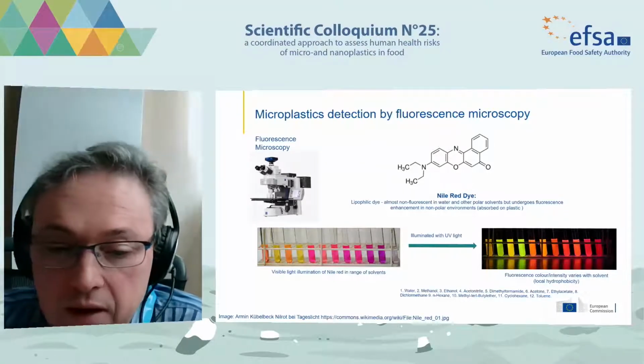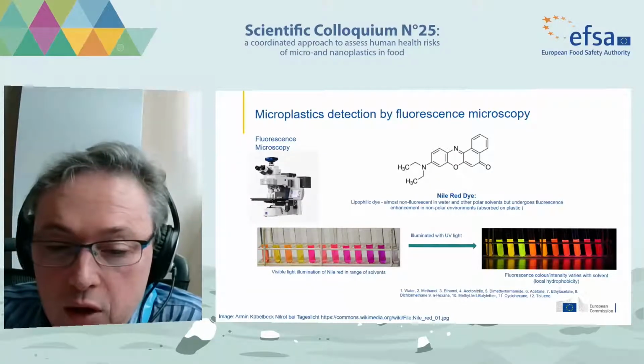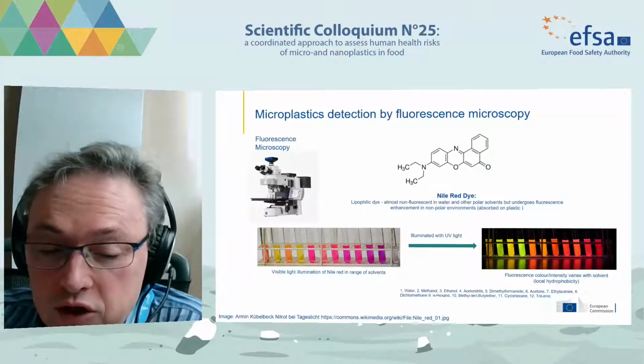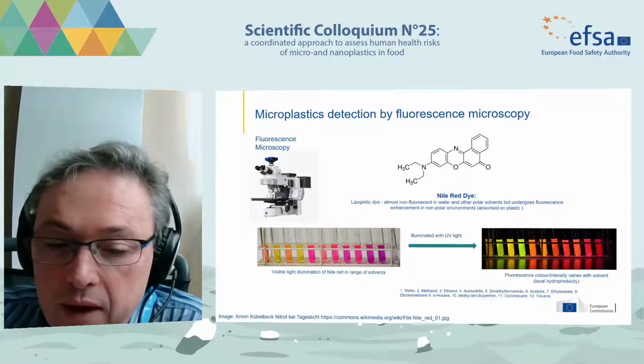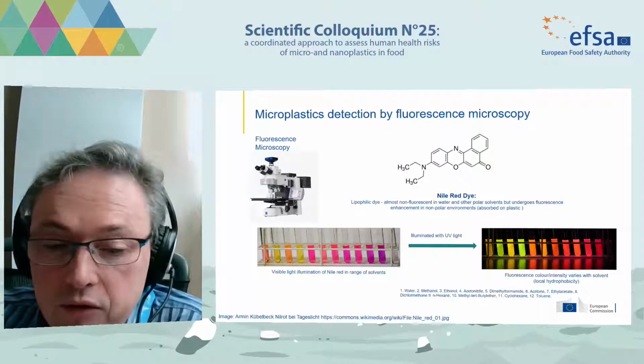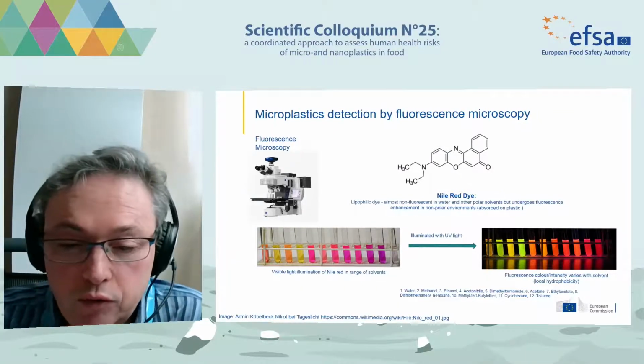In the photograph on the left, the dye is dissolved in a range of solvents, which, viewed under natural light, show a range of colours depending on the solvent used. When illuminated by UV light or near-UV light, these differences are seen to be greatly enhanced, with the aqueous solution showing only very weak fluorescence.